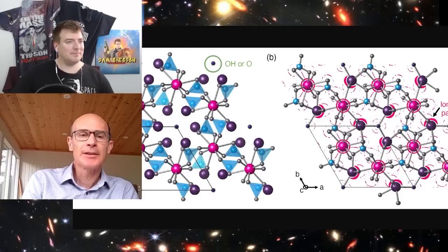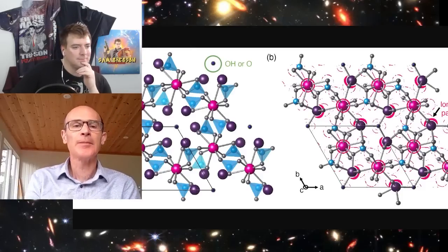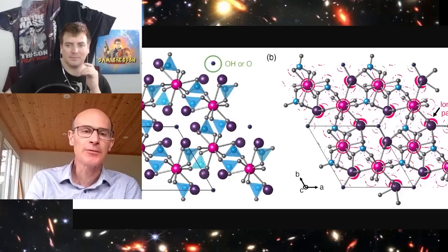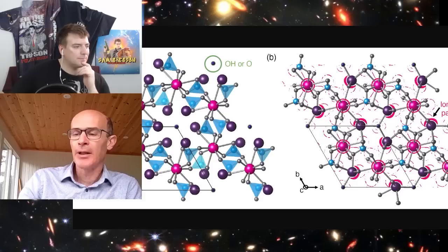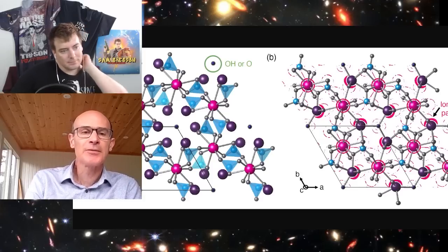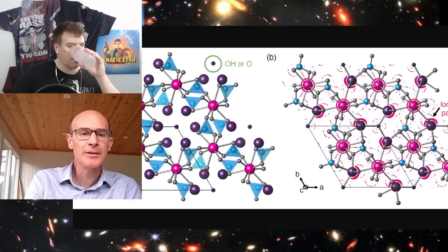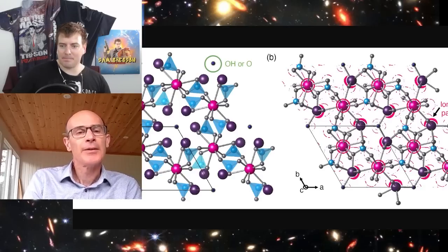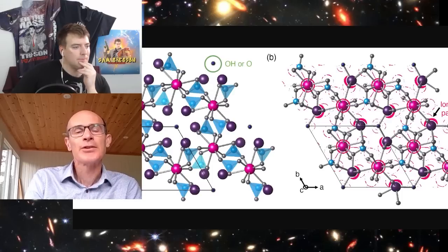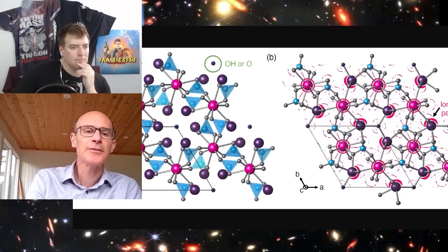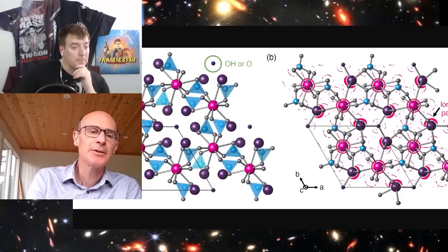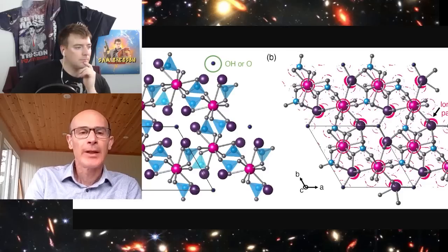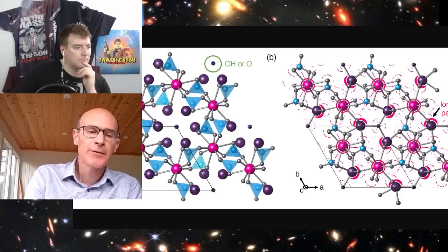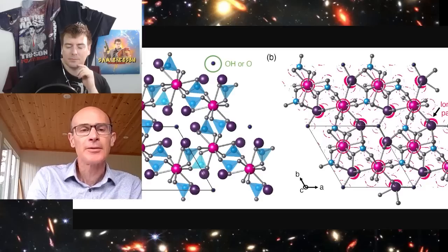Okay, so apatite is a mineral. So the apatite mineral is a calcium phosphate, and that has calcium 2+ ions and phosphate tetrahedra. You can see those in blue there. This structure can accommodate other ions. So, for example, in this case, all the calcium 2+ ions in the original mineral apatite have been replaced by lead. So you can make lead apatite. And there are some additional ions, as well as the phosphate groups that are in the blue tetrahedra on your diagram.